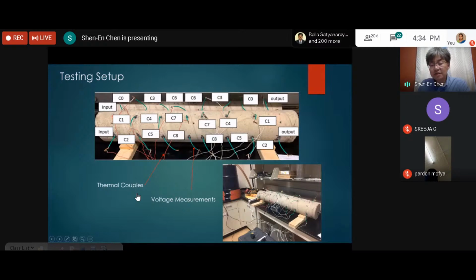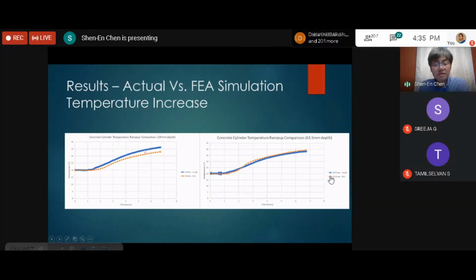We have the heat drum that heats up water that circulates through this pipe, and that would increase the temperature. Again, we use finite element simulations, and also use infrared to show exactly what's happening with this concrete element. So we were able to heat the elements up to 100 degrees Celsius. And then during the heating process and the cooling process, we do the correlation between the voltage change. So here is the temperature change versus finite elements that we did on those concrete cylinders that we made for the energy storage. These results are at room temperature, so there is no insulation elements to this particular experiment.